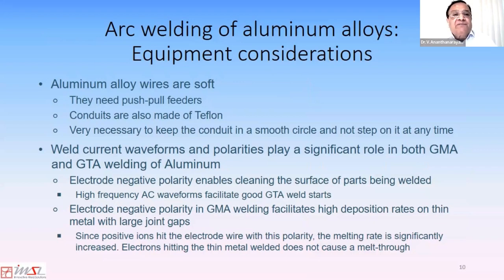All arc welders for aluminum need push-pull feeders because the alloy wires are soft. You cannot just push the wire into the weld gun conduit like you push a steel wire. You need a push-pull feeder, and the feeders are very close to the contact tip in these guns. And the conduits are also made of Teflon. So it's very necessary to keep the conduits in a smooth circle and not step on them, and handle these welding conduits and welding setups very gently when you're welding aluminum.